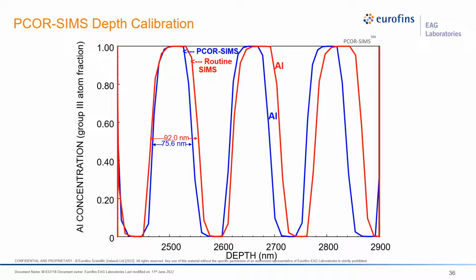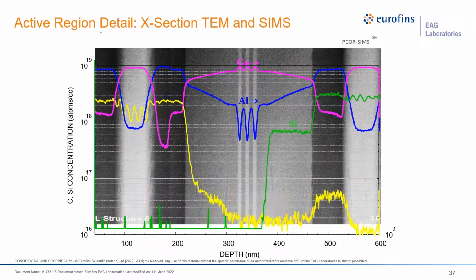With PCOR SIMS, this weakness is addressed by the empirically derived sputtering rate function that I showed earlier. This determines the instantaneous sputtering rate for each data point based on the measured aluminum content, or indium content for InGaAs active layers. Armed with this approach, compensation corrections are made for variations in sputtering rate throughout the VCSEL. The accuracy of the PCOR SIMS protocol in determining layer thicknesses can be seen in this slide, which is an overlay of a PCOR SIMS analysis of the active layer of a VCSEL with the cross-section TEM micrograph of the same region. The agreement in layer thicknesses between the PCOR SIMS and the TEM is quite good.